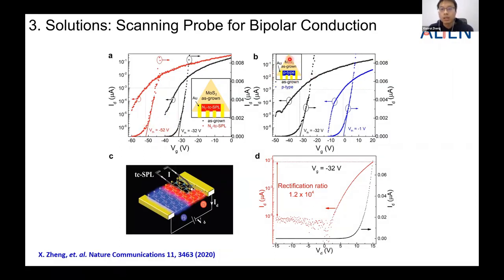And we also did p-type doping of the entire channel. Compared to the pristine transistor, for the p-type doped transistor the threshold voltage has been shifted to the right. This is also consistent with the entire p-type doping. So far, we are able to prove that our scanning probe lithography n-type doping and p-type doping both work in a real device. So the next step, we patterned a p-n junction by doping only half of the channel into p-type and the other half of the channel into n-type, and we can create it.